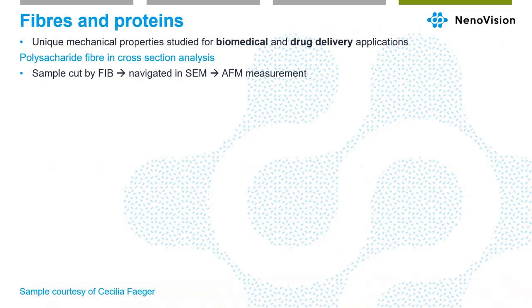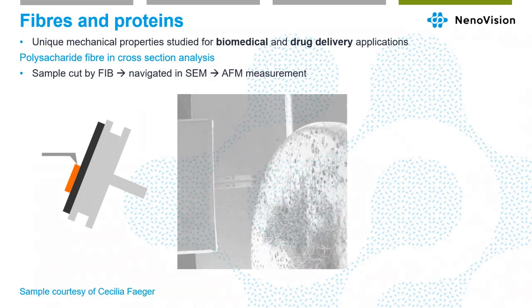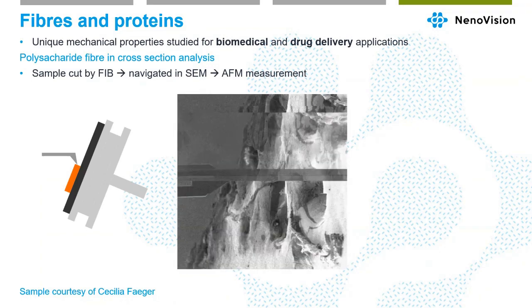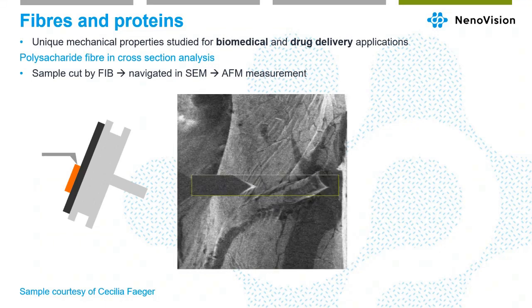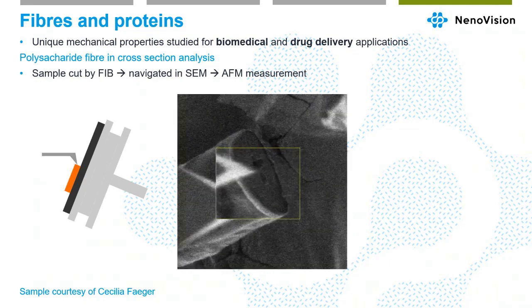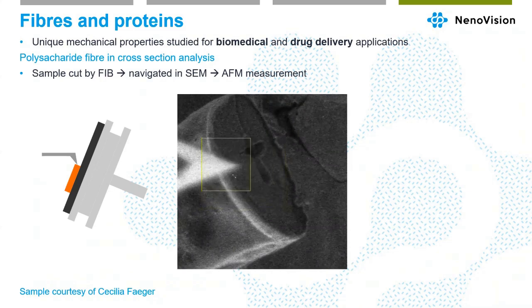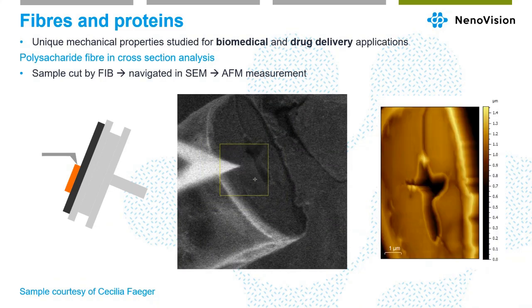Here is an example of polysaccharide fiber. It was measured in the cross section. First, the fiber was cut by focused ion beam. And then we navigated in the tilt in SEM, and then we could do the AFM measurement. The navigation here, as you can see, was quite difficult. And so we are now in the contact, and we were able to measure the topography with energy dissipation. So now we are able to have a look inside of the fiber, how it looks like and what happens there.